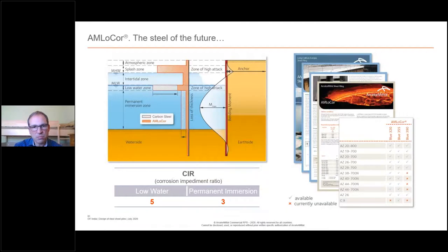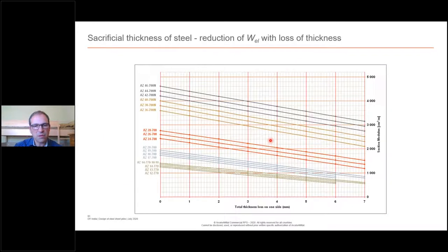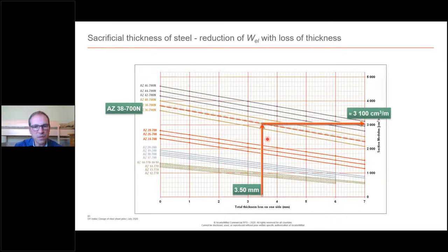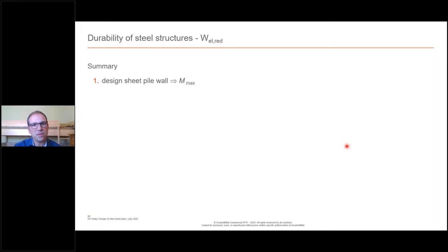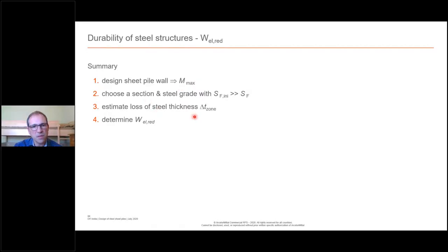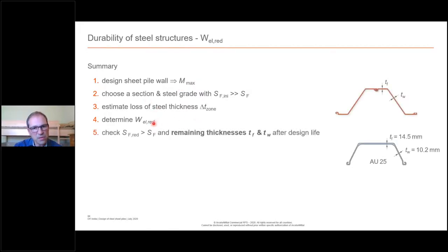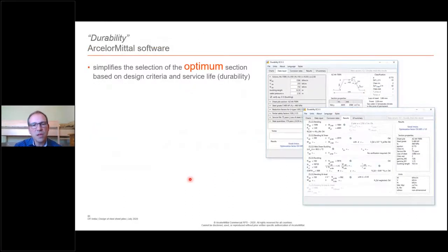And then if I go to the next slide, okay, how to determine the reduced section properties if you assume that the sheet pile will corrode. You have these graphs from the manufacturers, and you select the sheet pile and how much thickness you lose, and then it gives you approximate reduced section properties. So this is, again, a summary. It's an iterative process. You design the sheet pile wall, you choose a section, you estimate the loss of steel thickness, you determine the reduced elastic section properties, and then you check if the remaining thickness is the same, because the flange thickness and the web thickness are not always the same. So this is an iteration that you can do.